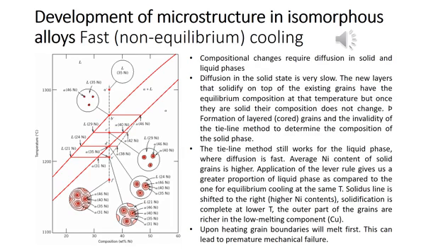Whilst for the solid, ideally the solid that should be formed should have 40% nickel, but in this case the new composition is around 42%, and this is because the earlier solid which was formed, which has a higher concentration, has no time to dissolve and be in equilibrium with the new solution concentration.